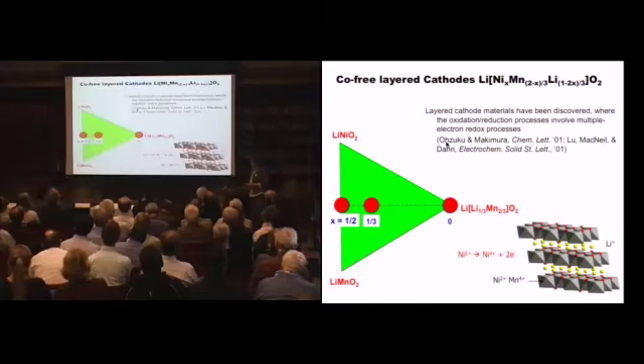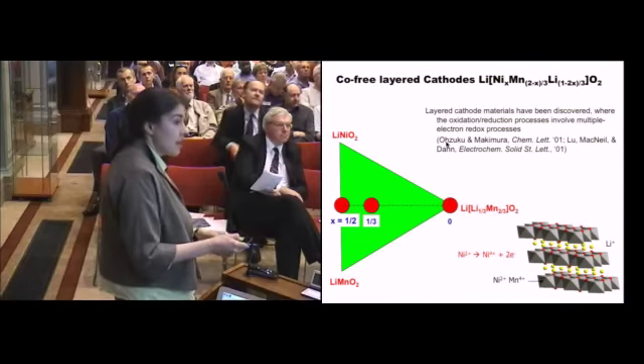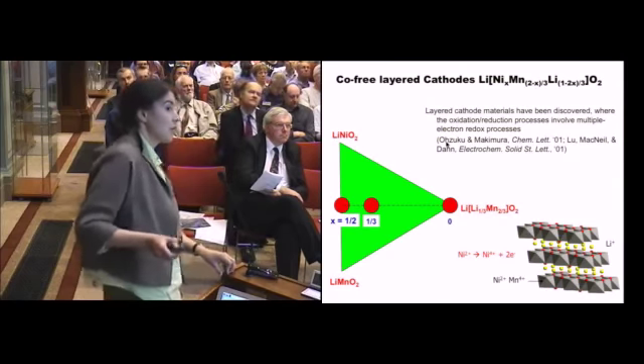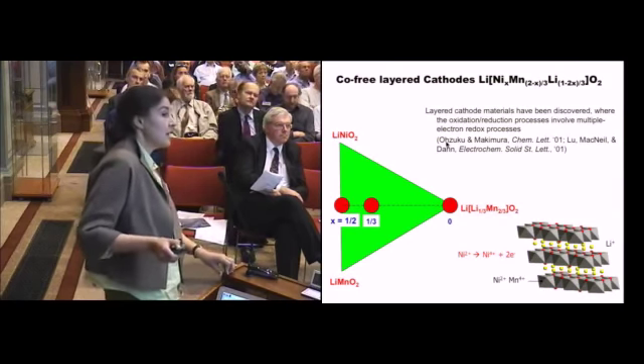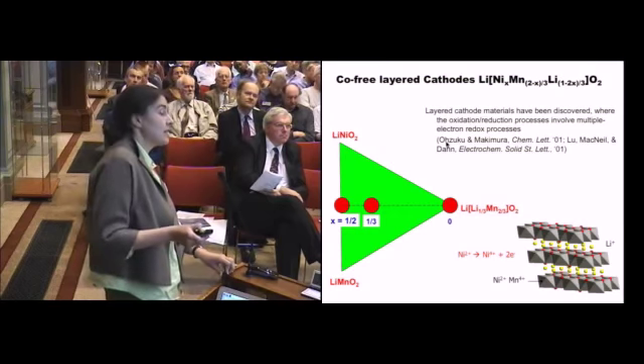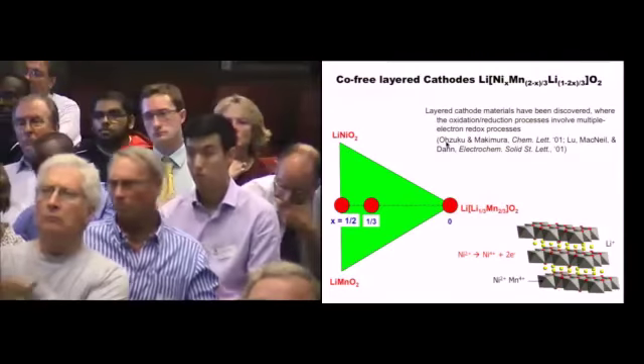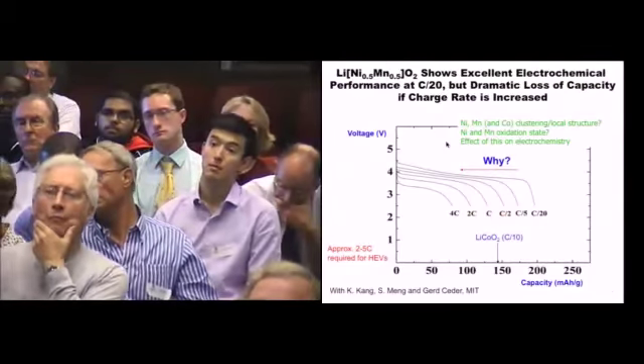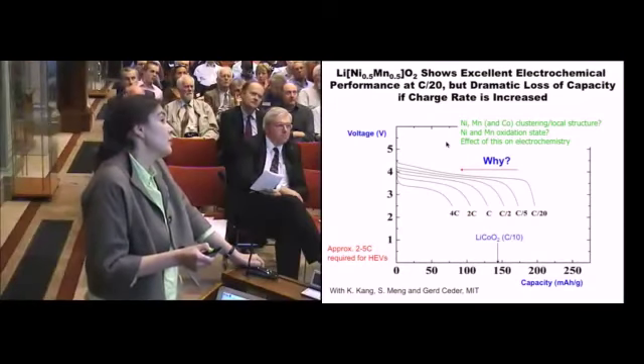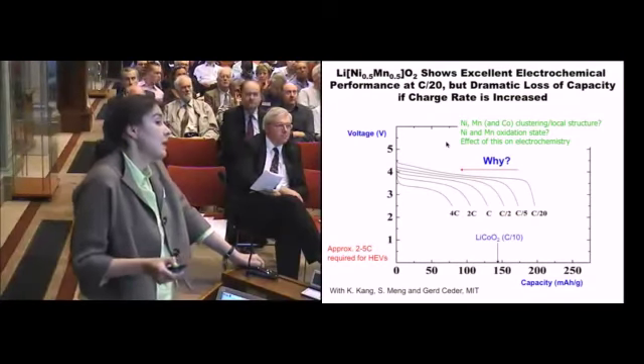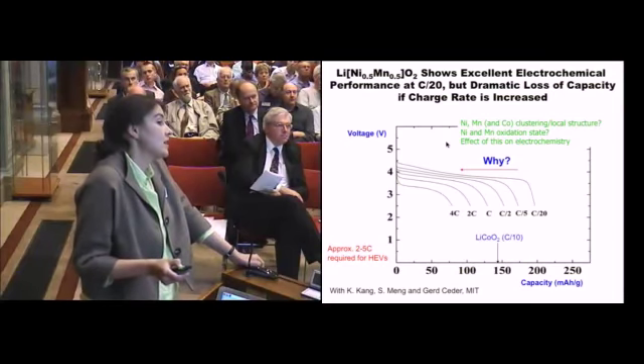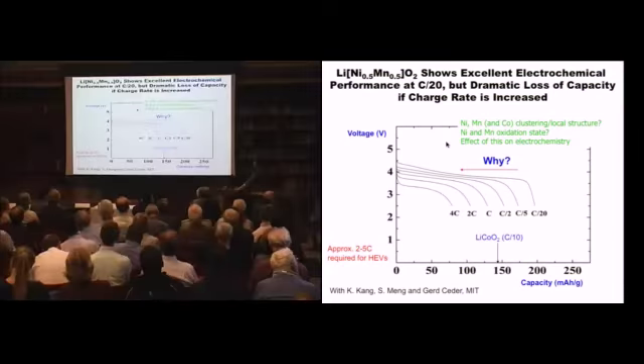So just to end, I want to give you one nugget of how these NMR techniques can be used to actually make new materials and improve them. I want to end by talking about these layered lithium cobalt oxide structures that I mentioned in the beginning. You can take the cobalt and replace it by manganese and nickel and make a whole variety of different complex structures. I just want to focus on one very simple one where I've taken the cobalt and put in 50% nickel and 50% manganese. When I charge this at a slow rate, so C over 20 means I take 20 hours, it gives you a capacity of about 200 milliamp-hours per gram.